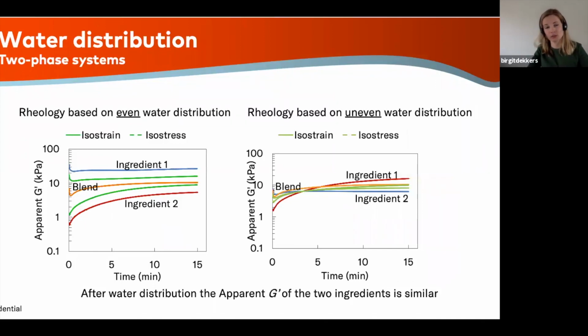And what we found during this research is that if you determine the rheological properties of ingredients assuming a water distribution that is even between two proteins, which we in the early days assumed, you see a very large difference in viscosity of these two types of ingredients. However, when we took into account the uneven water distribution that we found during our research with the confocal scanning laser microscopy and the time domain NMR, the rheological properties of these ingredients were actually much closer to each other, much more similar. And this is something that we thought is very interesting, that you need viscosities that are close to each other to be able to deform and align these types of proteins to create a fibrous structure, which we of course were interested in.